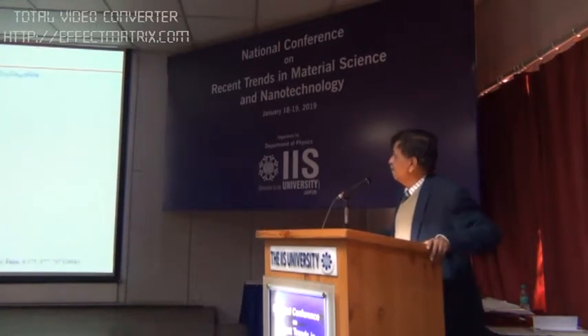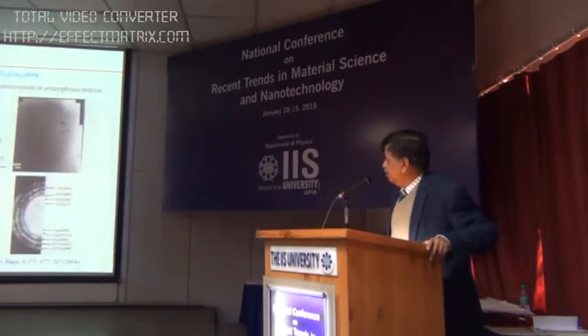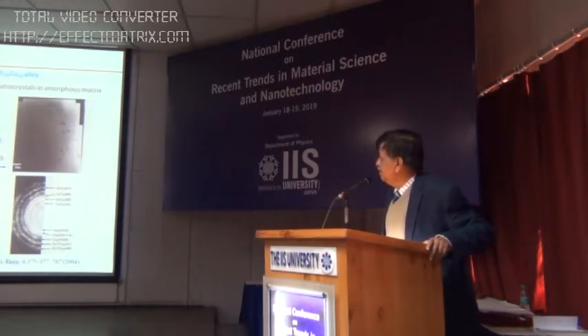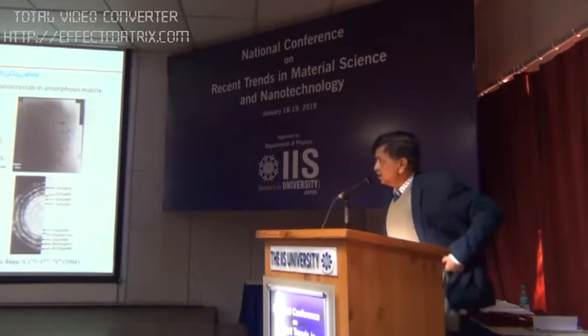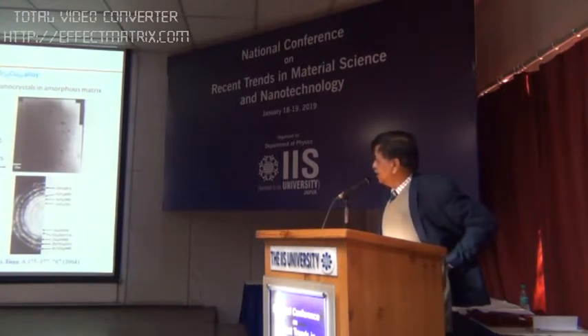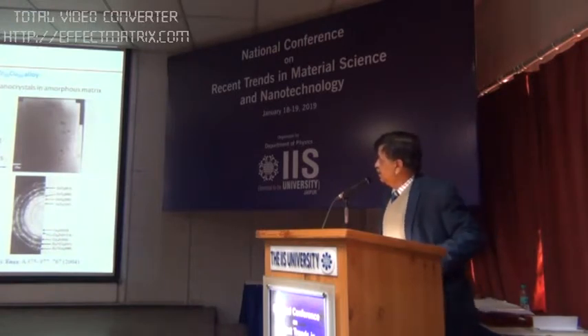So you can see that this is actually the bright field image of a glass after annealing. You can see a few nanocrystals dispersed in the amorphous matrix, and you can see the selected area electron diffraction pattern in which these nanocrystals have been characterized, or their phases are identified, by selected area electron diffraction pattern.